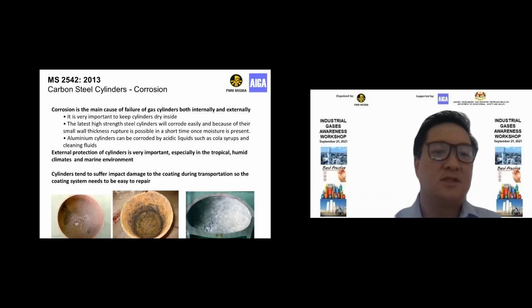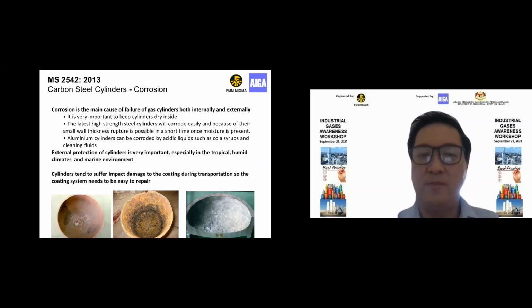Okay, carbon steel cylinders, corrosion. It's very important for us to keep the internal cylinder dry. Production processes are important to ensure that the gas we put in the cylinders is safe. What we have found is that the higher the pressure, the higher the strength of steel that is used, and the more susceptible it is to corrosion.